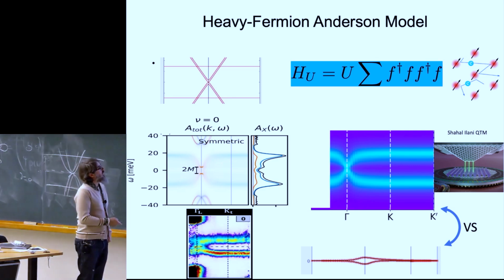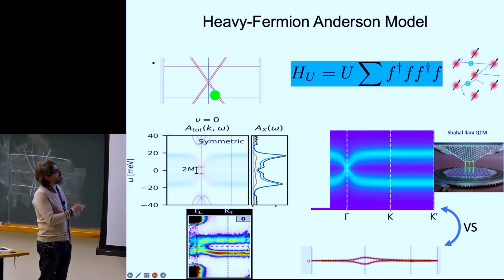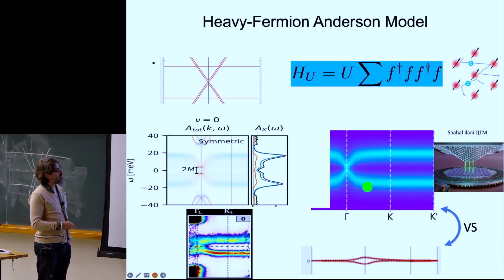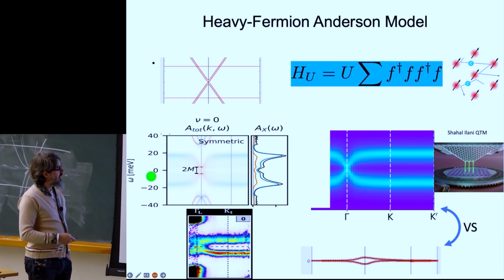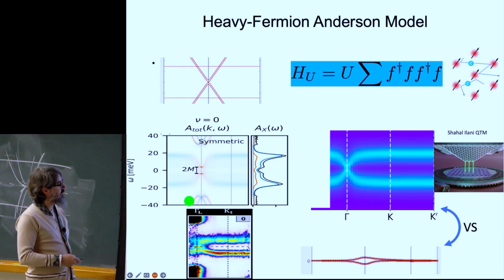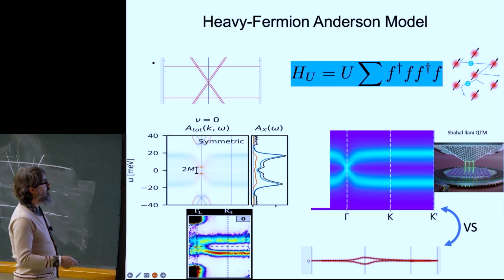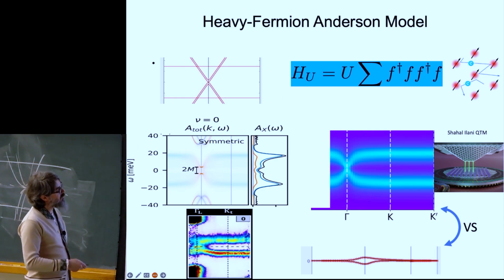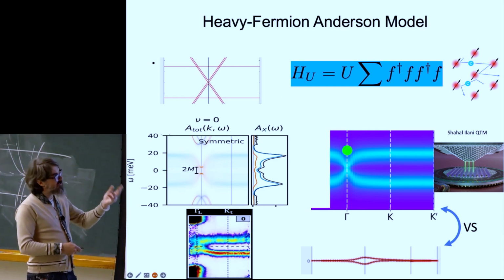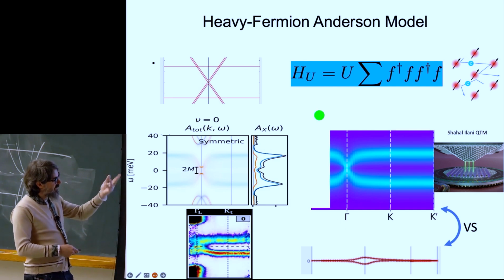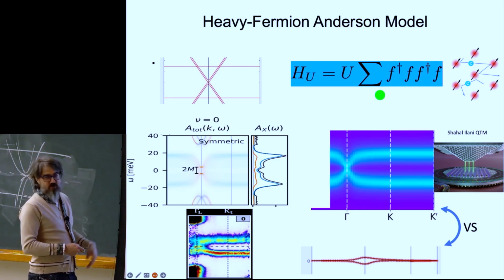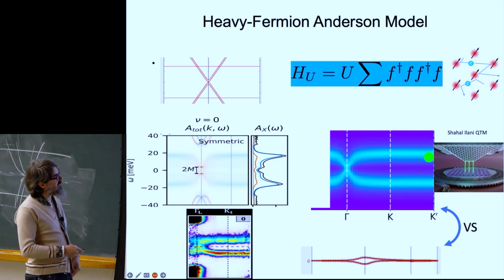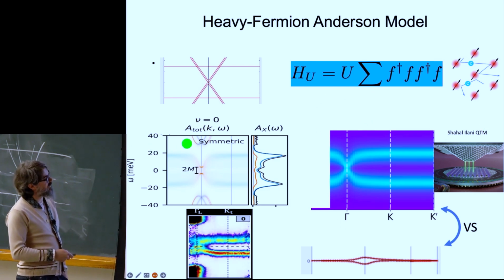So then this is just an approximation that you get by putting zero hybridization between the F and C electrons. But then what you can do is full DMFT, which has been done by the groups of Giorgio Sangiovanni, Tim Wehling, Roser Valenti, and Antoine Georges. So basically what you do is you actually treat the system, you get the self-energy, so you can get lifetimes, etc., in the approximation of the self-energy being K-independent. And this is a spectral function that you get.